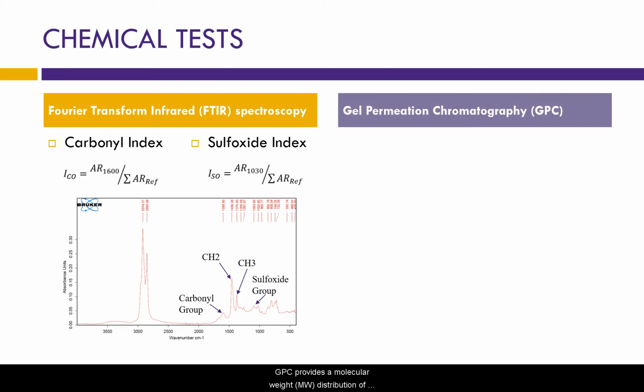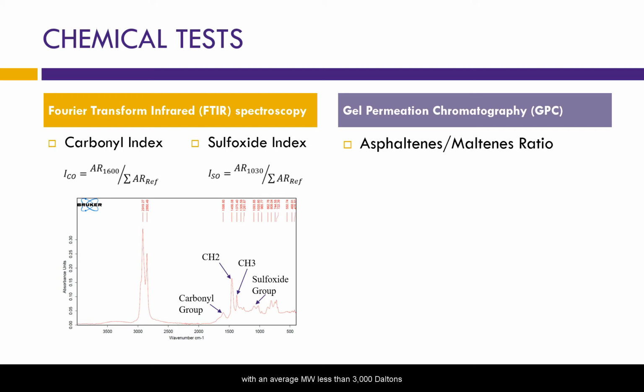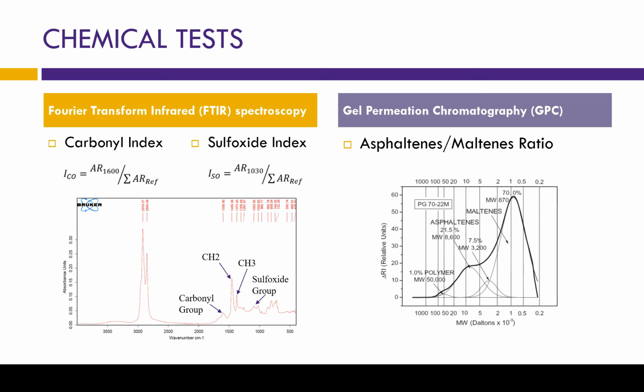GPC provides the molecular weight distribution of asphalt binder components. The maltene or low molecular weight components have an average molecular weight less than 3,000 daltons, while the molecular weight of asphaltenes is between 3,000 and 15,000 daltons. Using this approach, the aging and brittleness levels of asphalt binder can be evaluated through the change in the ratio of asphaltenes and maltenes molecular weight.